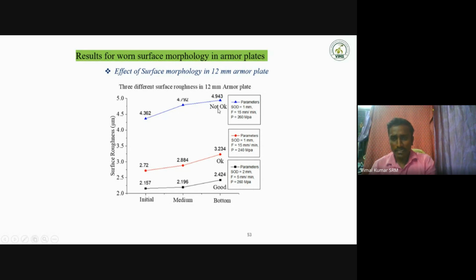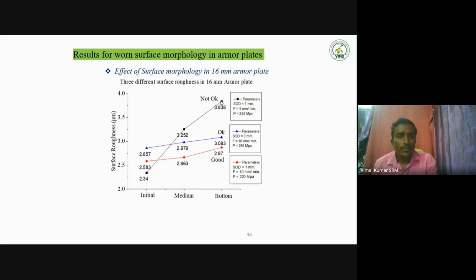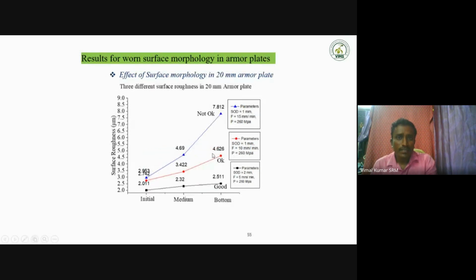Already we tried a number of trials and we also achieved this. For this initial stage, we can get this kind of values. So 4.9 is easy to identify with our vision, the number of traces in the cut surface of the water jet machine, the cut surface of our research materials. So these are the results on surface morphology of armor plates. These are the surfaces influenced by different parameters. The same for a 20 mm plate.